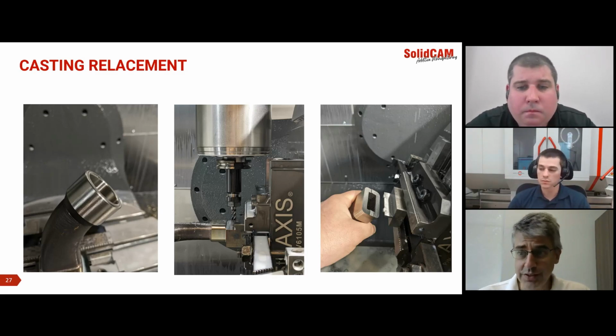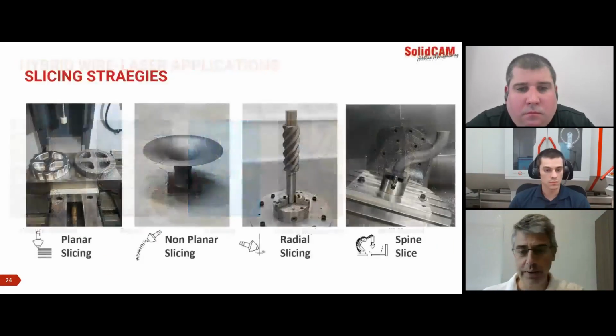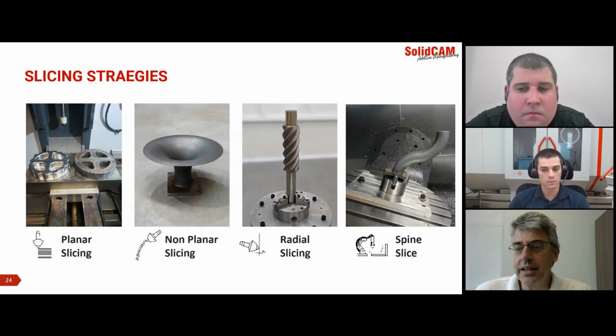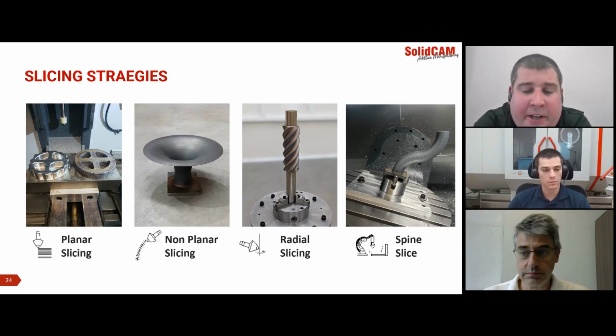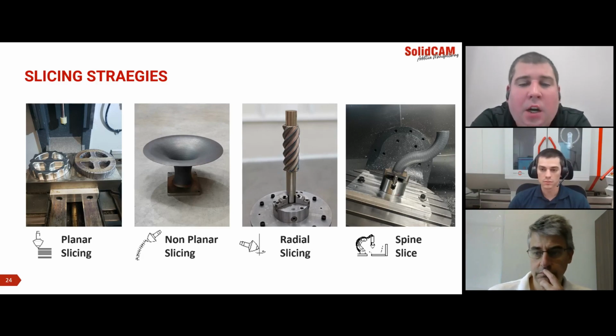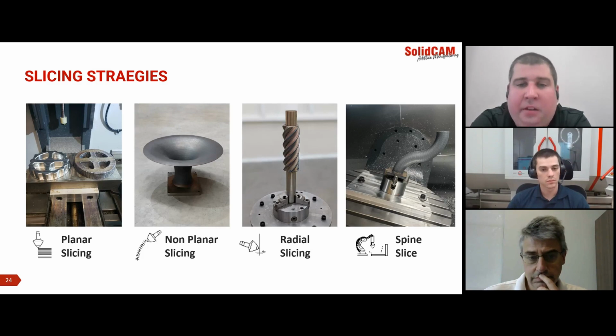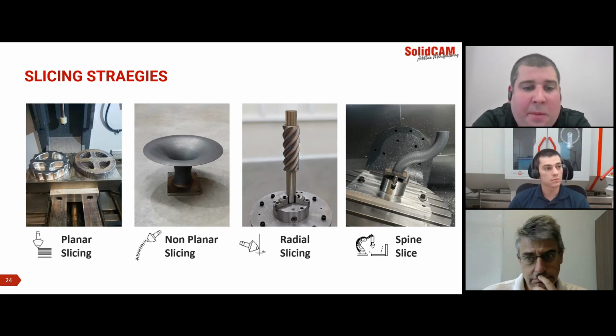This one's a good geometry question. On the spline-based slicing of the tubes, and you showed one of the tubes, it's kind of wound back and forth. On that spline-based slicing, how are you managing the different bead heights between the inner radius and outer radius? So one of the unique things about this toolpath is we're giving it a centerline spine curve, and based on the relationship between the spine curve and the actual geometry, meaning the internal radius versus external radius, we give the toolpath a slope function. This allows us to give it a nominal wire feed rate and linear feed rate, as well as a minimum and maximum.